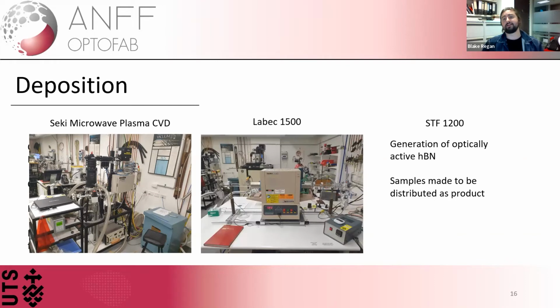Our final capability in terms of deposition is the STF 1200, which is just another tube furnace. However, this one we've specialized in the growth of optically active hexagonal boron nitride. For those of us who aren't familiar with hexagonal boron nitride, it's a two-dimensional material with a range of emission properties depending on the kind of emitter that's grown into it.